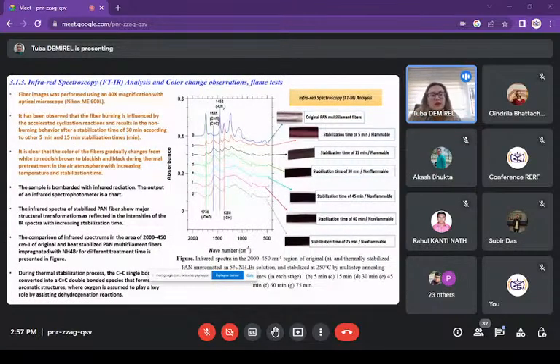I used the flame test analysis, and it has been observed that the fiber burning is influenced by the accelerated cyclization reactions and results in non-burning behavior after stabilization. After stabilization, 30 minutes compared to the other 5 minutes and 15 minutes stabilization times. It is clear from the pictures on the right that the color gradually changes from white to reddish brown, blackish, and black during thermal pretreatment in an air atmosphere with increasing temperature and stabilization time.